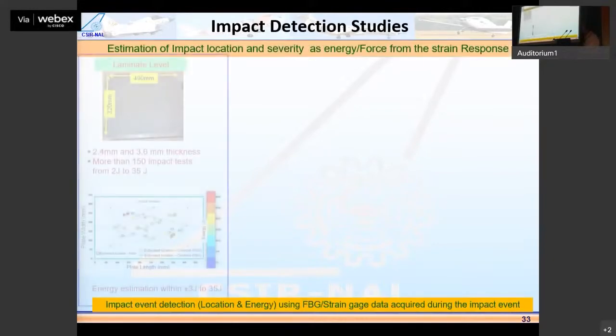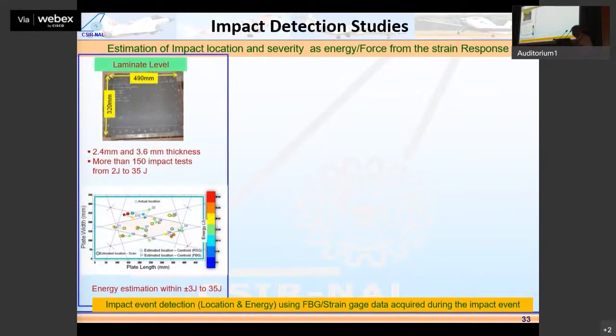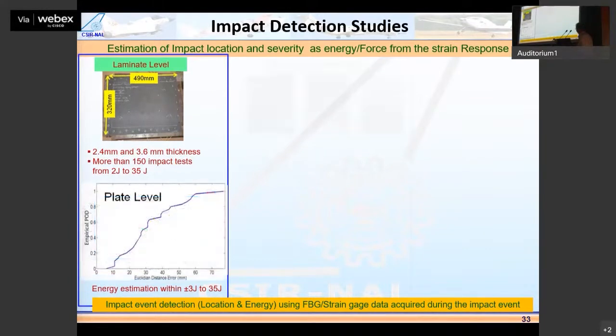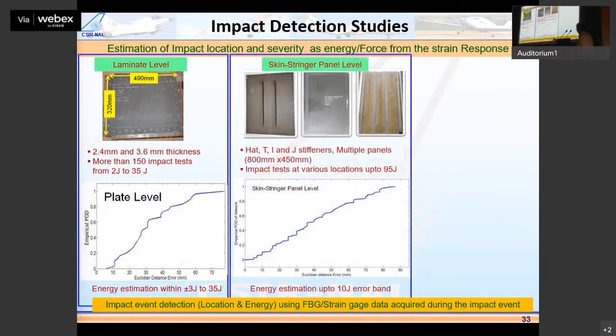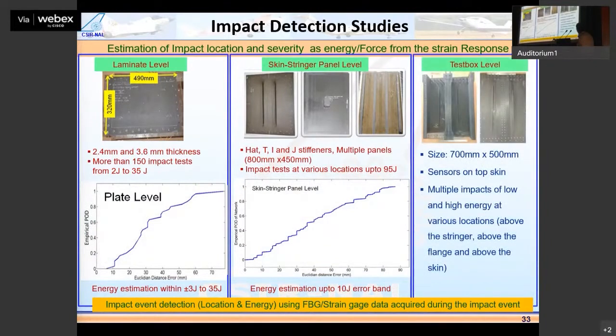When we were part of the Center of Excellence, there was a program called ACE-COST, ARDB Center of Excellence for Composites. So we had a program with this. Can we immediately, as soon as an impact takes place, find out the location and damage in a structure? We did a lot of studies, starting from flat laminates to stringer panels, and for all we can see the probability of detection at nearly 90%. Within 50-60 mm, you can find out the location. So imagine I have a 10 meter or 20 meter wing, and if I can tell you the location of a damage within 50 mm, I think it's a marvelous technology which we have.